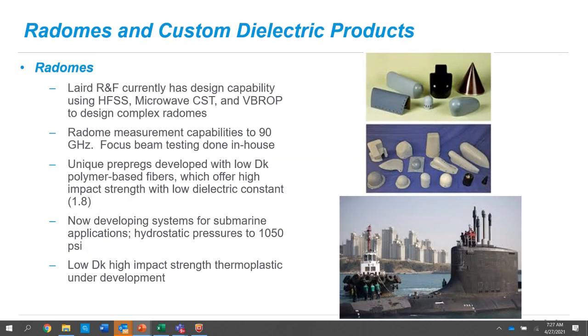I just mentioned Radomes, not a lot here, but we do a lot of impact testing on our Radomes and our Radome materials. We're looking at, I think the innovations we're trying to make there, we're using polymer-based fibers, so things like Spectra and Innegra, which is a polypropylene fiber. Spectra is a high-density polyethylene fiber. They're low dielectric, so they're good for Radomes, but they're also very tough and offer you good impact resistance.